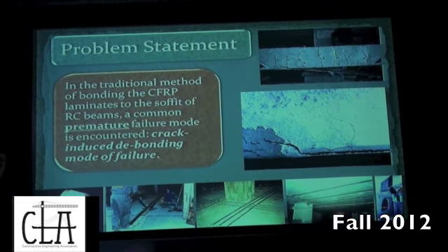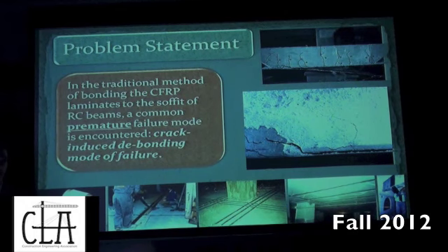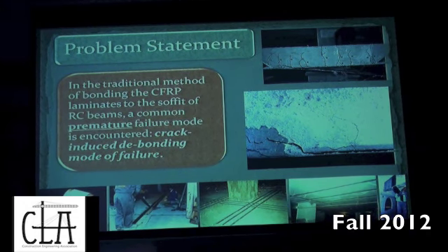Okay, so basically the main problem is that the traditional method of bonding the CFRP, they're usually bonded at the bottom of the concrete RC beams. What happens is there's a common premature failure, which is called the crack-induced debonding failure. And this is what we're trying to reduce.